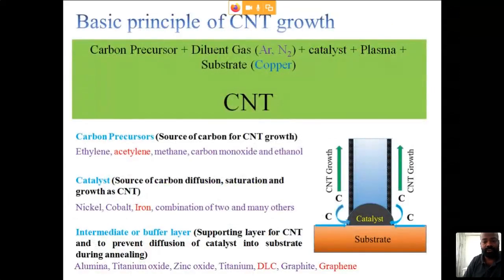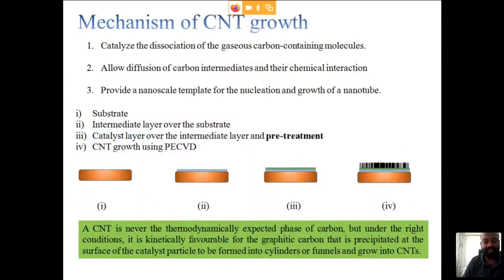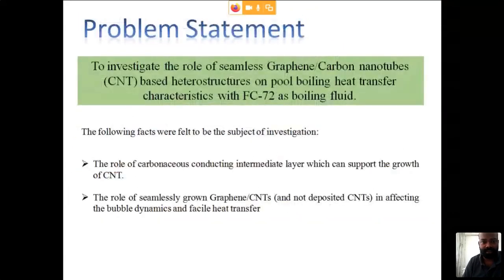Now initially we have used carbon nanotube. So what is the basic principle behind this carbon nanotube growth I have shown here. Now we have used the CVD technique, PECVD technique, plasma enhanced CVD technique, to grow the vertically aligned carbon nanotube over the copper substrate, and in between we have used the graphene intermediate layer. So this graphene also we have grown using the CVD technique only. This is the mechanism of CNT growth on any metal surface.